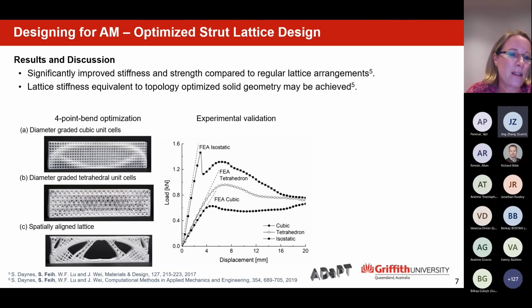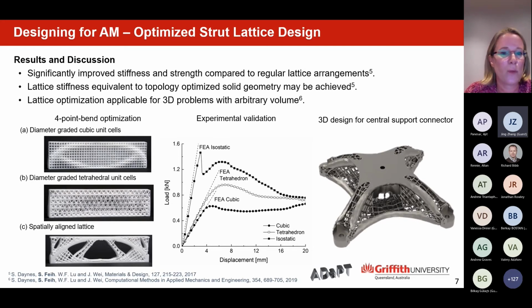And we can see in that case that the finite element, or the experimental predictions, increase significantly in stiffness and strength. And we can also use these kind of algorithms for full 3D problems with arbitrary volumes and apply the lattice generation algorithm to that. The nice thing here as well is that the structure Ajit was talking about was supportless. Well, in this case, we would actually utilize the lattice structure as our functional support. So it has a role to play in the topology optimized design. There's no need to remove it afterwards. So therefore, we have basically a multifunctional lattice here acting as both support and load bearing member.